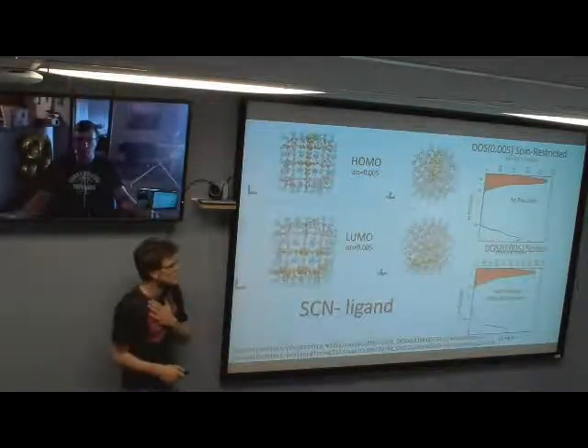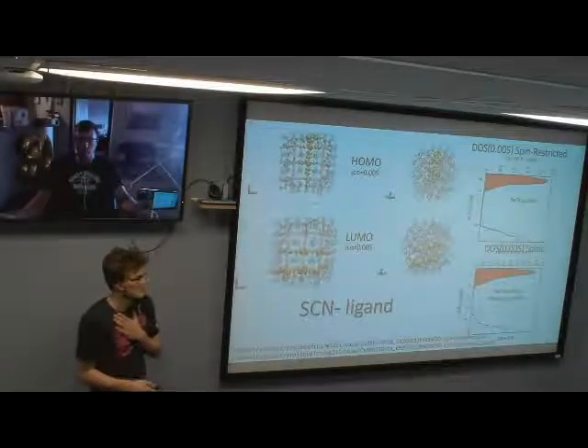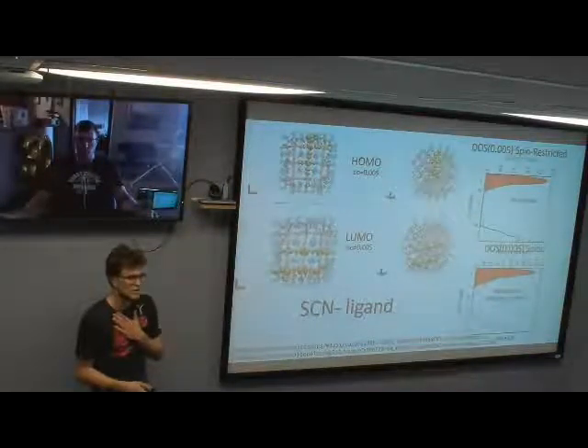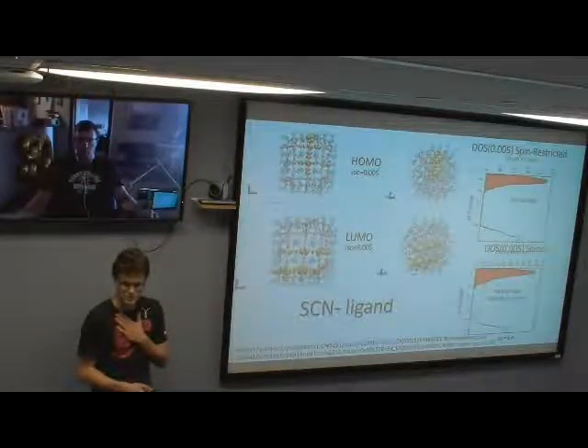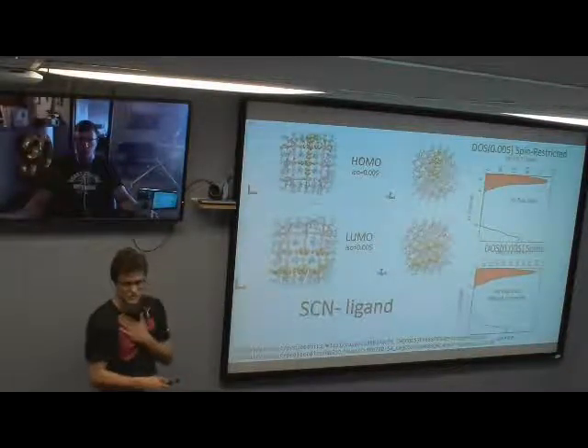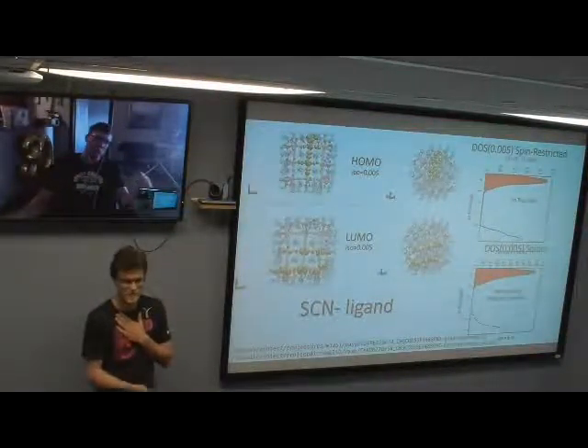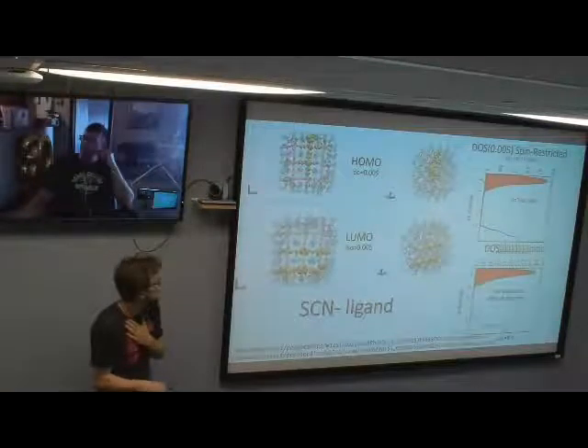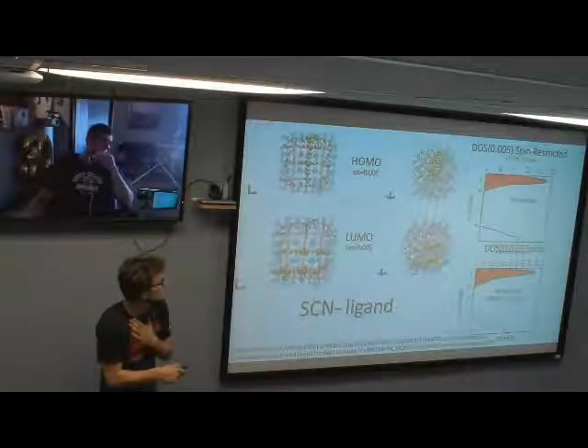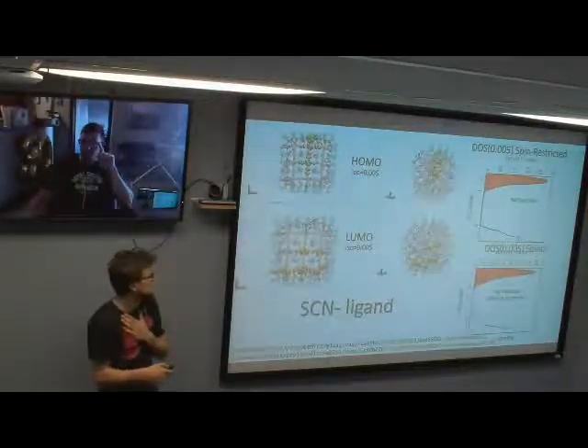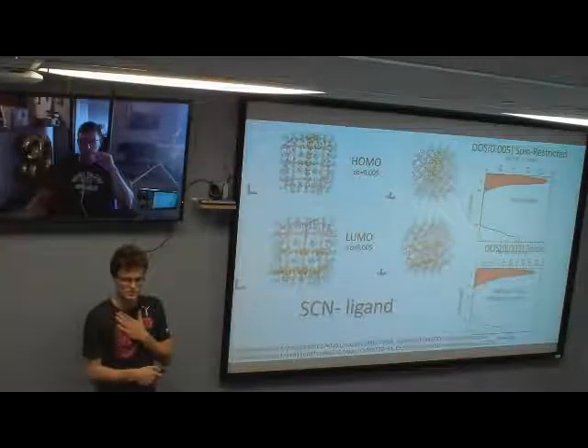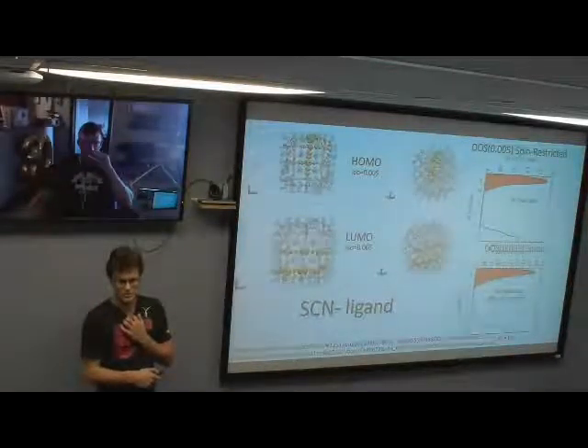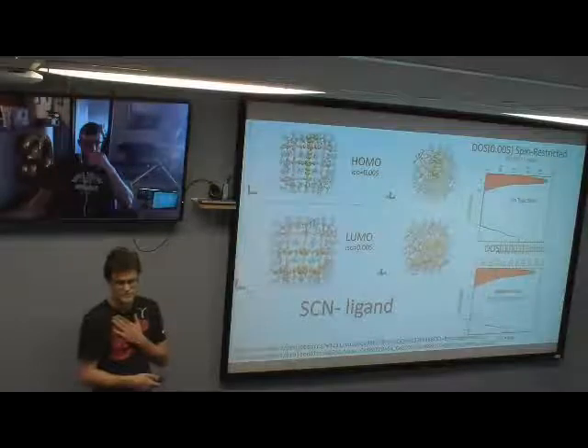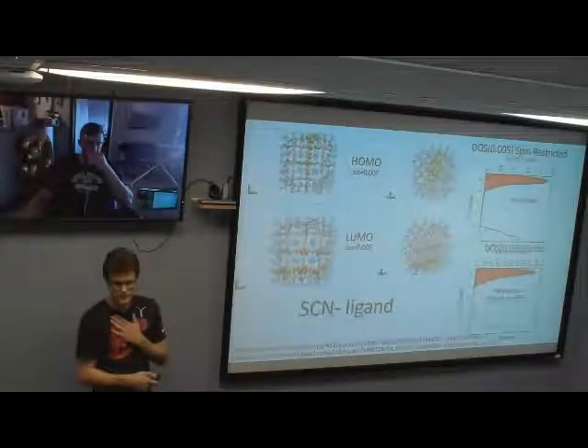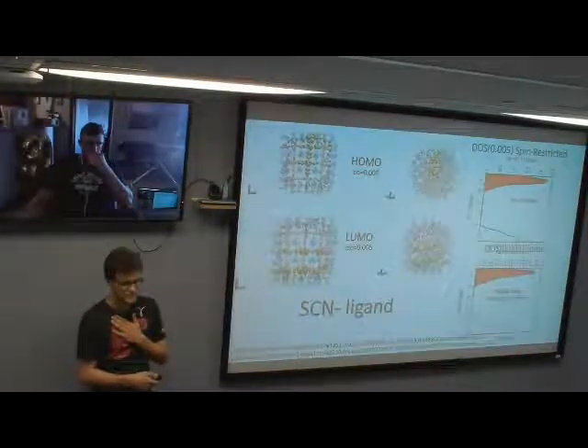In the paper that we were following, they noted a consistent 5 nanometer blue shift in their spectrum. Is that after substituting the ligands? Yes, after they do the treatment. From the density of states, I haven't done the calculation yet, but it doesn't seem like it changed that drastically. But because you have only a single ligand. Yeah. If you change all carboxylate groups to isocyanate, you probably will see a much more significant change.